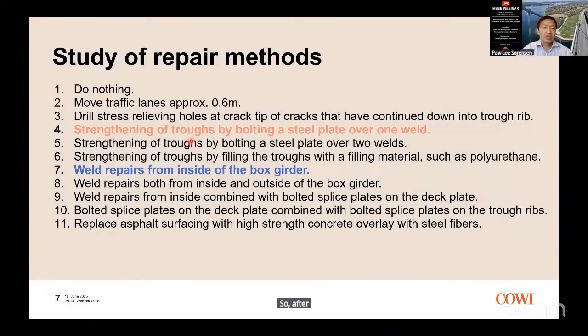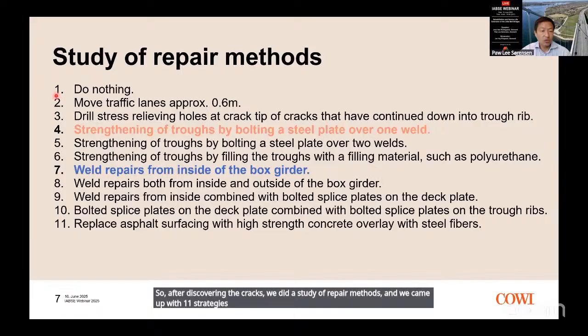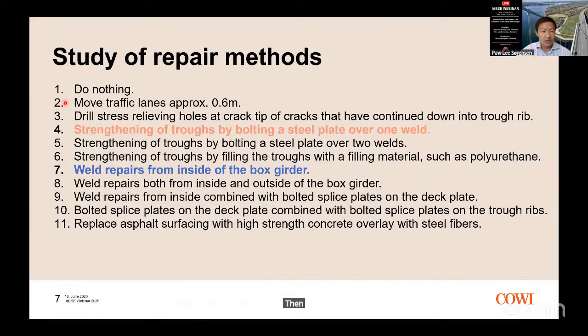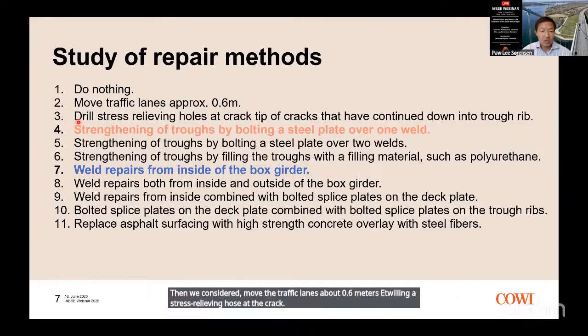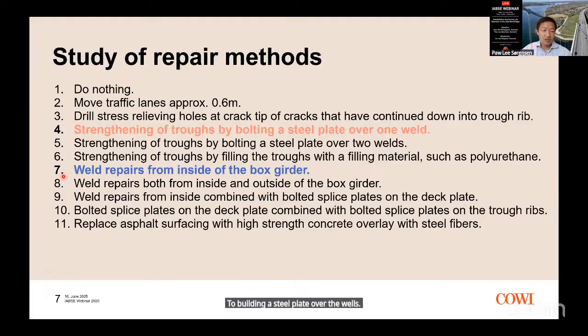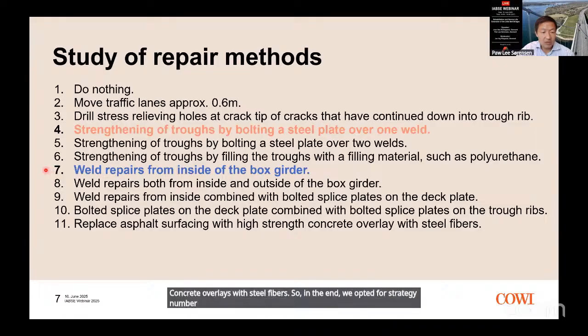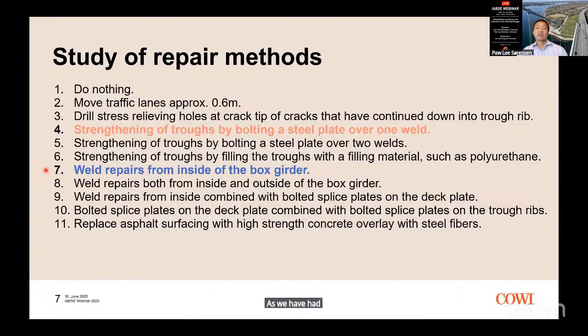So after discovering the cracks, we did a study of repair methods, and we came up with 11 strategies. The first one was to do nothing. Then we considered moving the traffic lanes about 0.6 meters, drilling stress relieving holes at the crack tip, bolting steel plates over the welds, also weld repairs from inside of the box in various forms, and lastly to replace the asphalt surfacing with a high strength concrete overlay with steel fibers. So in the end, we opted for strategy number 7, weld repairs from the inside, as we have had good experiences with this method on previous projects where we have seen fatigue cracks.